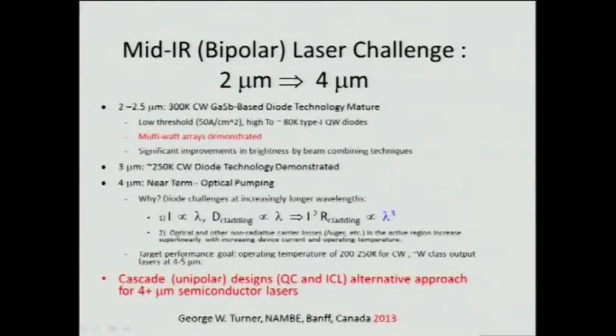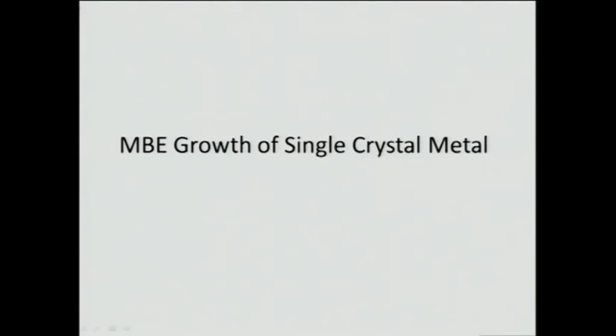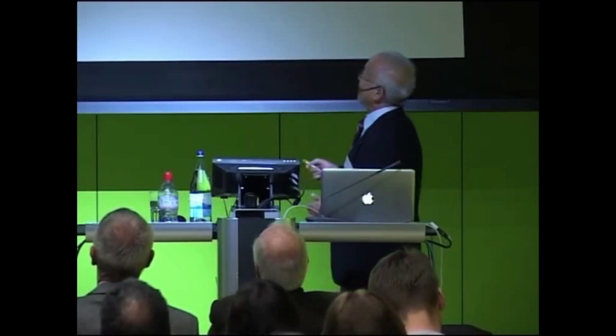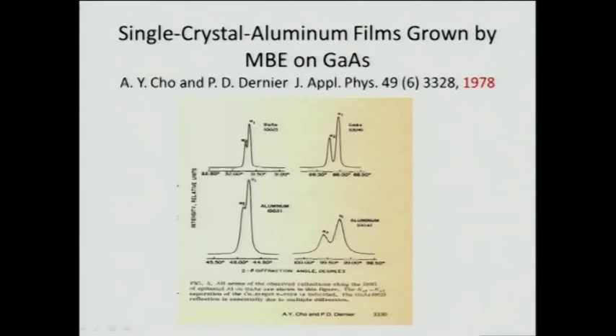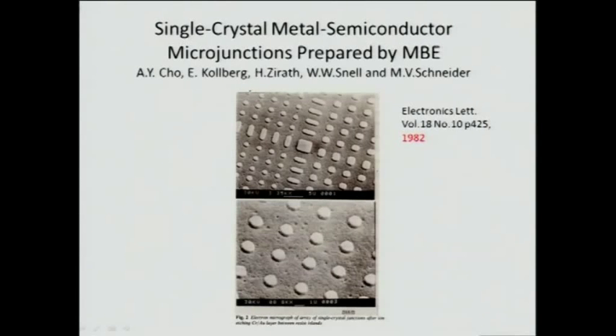And therefore, when we go to wavelengths above 4 microns, we would like to grow quantum cascade lasers for that wavelength regime. I also like to mention a little bit about another new development in MBE, growing single crystal metal films on gallium arsenide or III-V compounds. This was first demonstrated in the early days of 1978, the growth of single crystal aluminum films by MBE on gallium arsenide. And then we made micro Schottky diodes, single crystal Schottky diodes, 2 microns in diameter here,